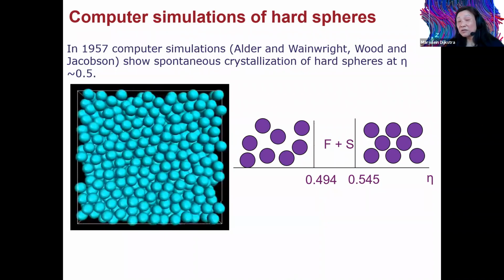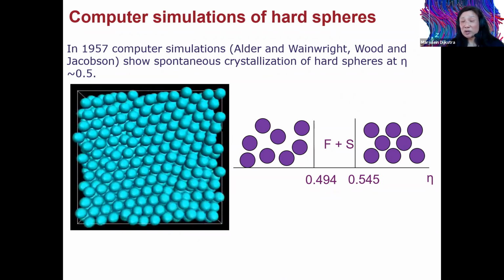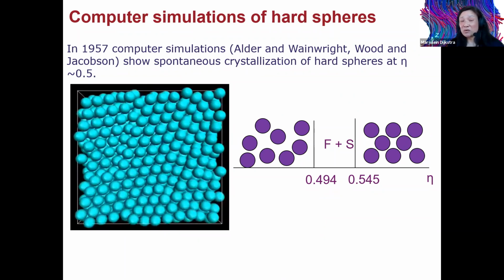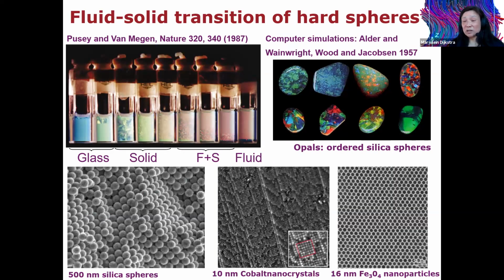However, already in 1957, computer simulation showed that there's a spontaneous crystallization of hard spheres. So if you compress hard spheres above a packing fraction of 0.55, they spontaneously organize themselves into a face-centered cubic crystal phase. And this was work by Alder, Wainwright, Wood and Jacobson. It took the experimentalists more than 30 years to synthesize colloidal particles that are perfectly spherical, well characterized, and that the sizes were sufficiently monodisperse, and to find also this freezing transition in colloidal hard spheres. And this work was by Pusey and Van Megen, who published this in 1987.